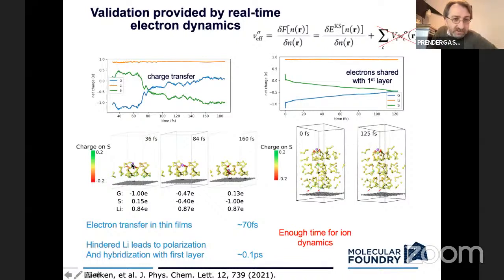And so what we notice here is when the lithium ion is very close to the graphene, it takes about 70 femtoseconds for the charge transfer to initiate. And then eventually the ion moves inward as well and becomes surrounded by the sulfur. Now, if we had a thicker sulfur layer and the ion was somehow pinned inside the sulfur molecule, what you see is a kind of saturation. And this amount of charge that moves is limited to this first molecular layer here. Even though you can see some polarization around the lithium ion, there's no net charge on those molecules. The net charge is actually localized in this region here. So there's some hybridization between the graphene and the sulfur, and then it saturates and stops.